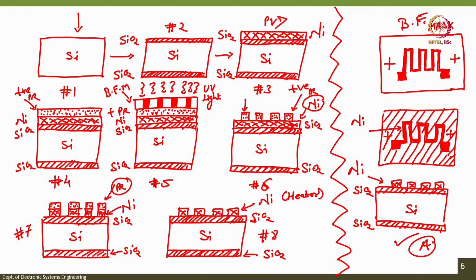You start with a silicon wafer, you go for RCA1 RCA2 cleaning, then you dry it, pre-bake it, then you load this wafer in thermal oxidation. You can use wet oxidation, you can use dry oxidation. As we know, for masking oxide, wet oxidation can be used, right. So, we will have about 0.5 microns to 1 micron silicon dioxide grown on the silicon wafer, followed by depositing nickel. Nickel we can deposit using physical vapor deposition, either thermal evaporation or electron beam evaporation, or it can be sputtering.